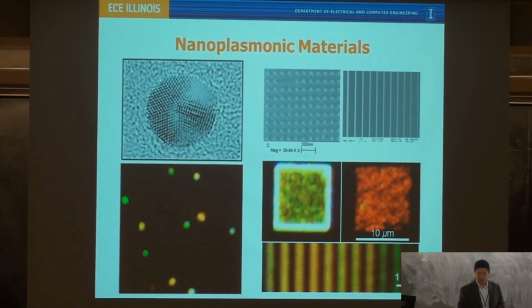But as an engineer, what we do is we use nanofabrication technology to make a highly ordered, highly uniform array of nanoparticles or nanowires, so they can have very defined, very controllable plasmon modes. For example, here what you're looking at is actually a scattering image of those arrays of nano dots made of gold. If you can make a very high uniformity fabrication, you can make a very uniform color out of the whole array. Okay, and here is the dark field scattering image from those nanowires. They actually exhibit different colors because they have different widths in this axis. So I believe from here to here you have 20, 30, 40, 50, all the way to 120 nanometers in terms of width.